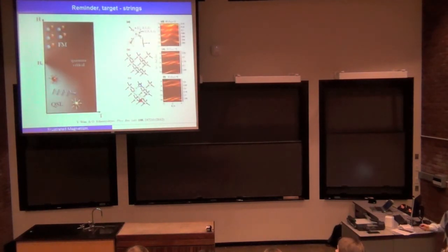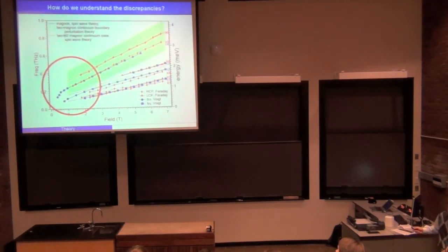And here we remember that we set up to look for signatures of quantum strings in this material. So now let's take a look at our data, see if there's any signatures at all of the existence of these quantum strings. We can see that in the high field region, the spin wave calculation can describe our data quite well. But as we go to lower and lower field, discrepancies start to appear, for example, here, and also there's an obvious change of slope here. This tells us that in the low field region, the spin wave theory does not describe the data at all.